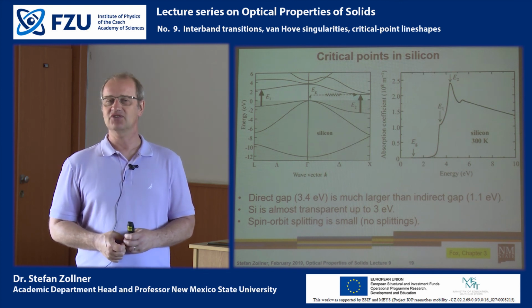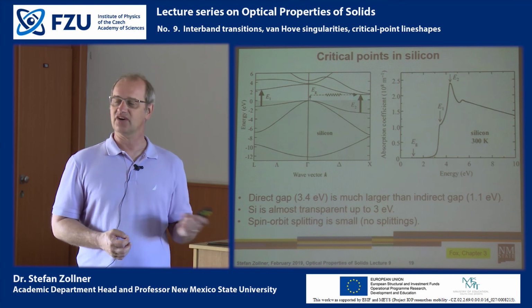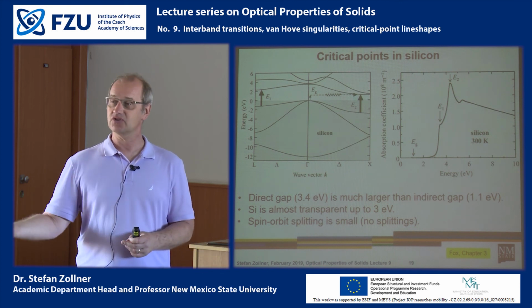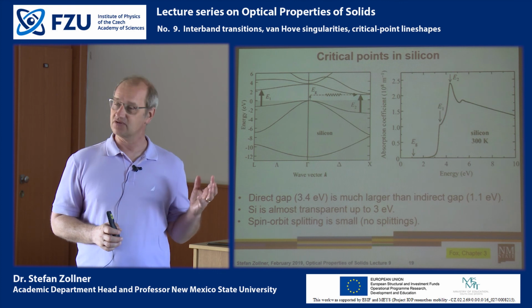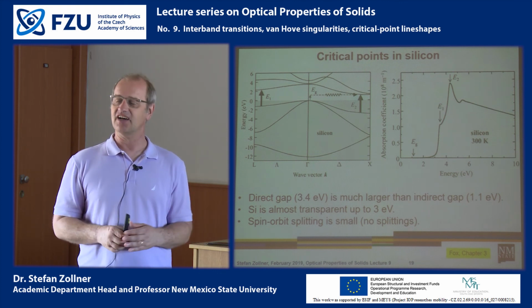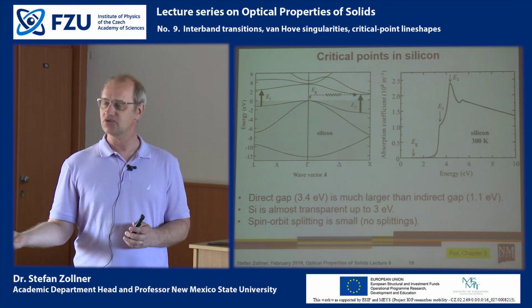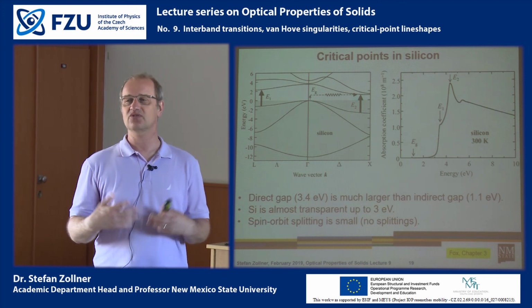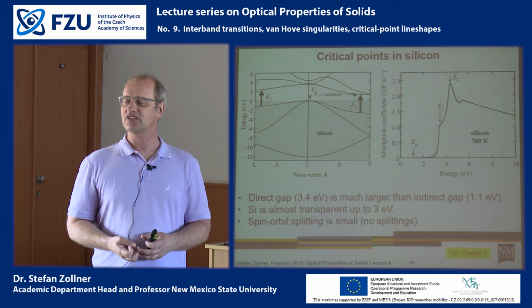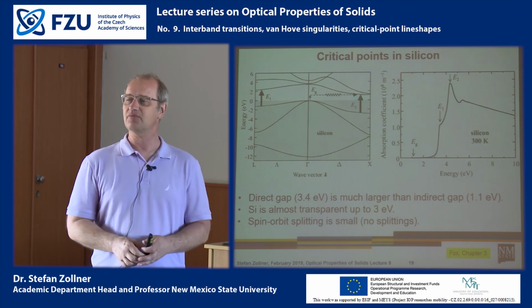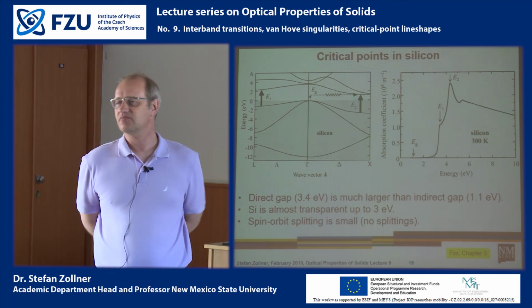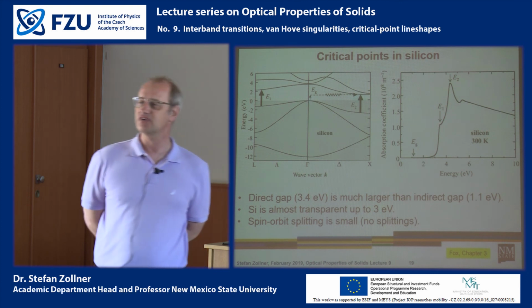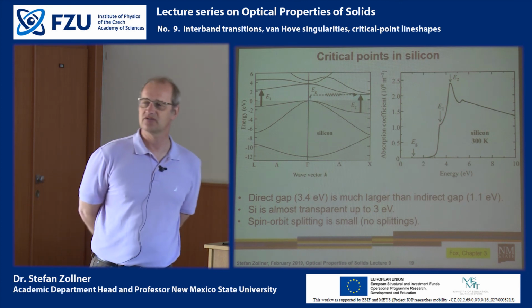For some spectral ranges, we can measure reflection. In other spectral ranges, we can measure absorption coefficients. And then we put those data sets together, and with Kramers-Kronig transformations, we can tabulate optical constants over a really, really broad spectral range.